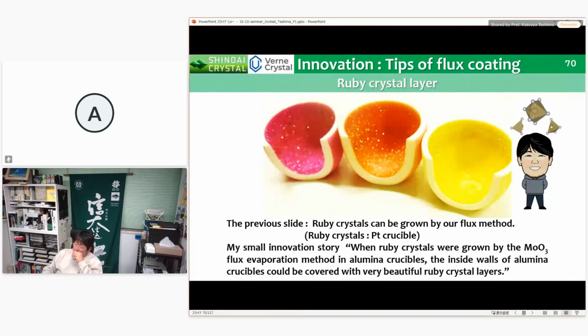In my innovative story, when ruby crystals were grown in an alumina crucible, the inside walls of the alumina crucible could be covered with very beautiful ruby crystal layers. This is the tip of our original flux coating.